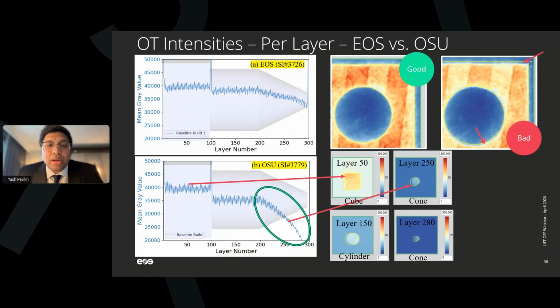So we need to now probe, and I need to wrap this one up quickly. I need to give you enough time as well. I'm 37 minutes in. We noticed this trend, which was different in the Ohio State University machine, especially for the last 100 layers for the conical cross section, because they had some mismatch on the OT, how it is capturing, and its mean gray value, right?